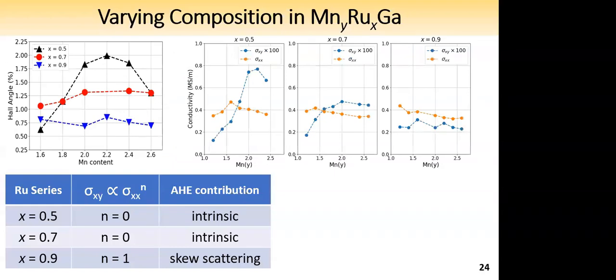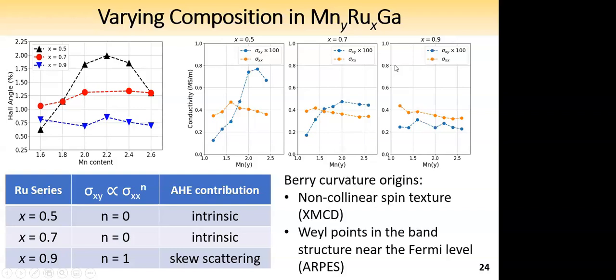So now coming back to the results of the anomalous Hall effect and the conductivities, I've summarized here that for different series, we have a different dominant anomalous Hall effect contribution. When the anomalous conductivity is independent of sigma xx, we have a dominant intrinsic contribution, and whenever they are basically proportional to each other, we have dominating skew scattering, which occurs for high ruthenium contents.